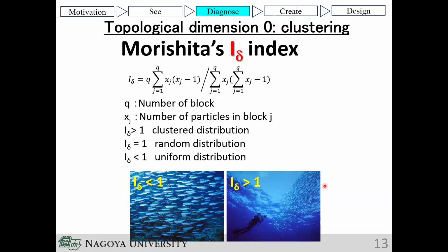Here, we use the Morishita's I-delta index. To evaluate spatial distribution, we employ the Morishita's I-delta index, originally developed in ecology, by dividing an image into Q grids and counting the number of entries x_j in each grid. The index characterizes the distributions. If I delta is larger than 1, the particles are clustered or localized. If I delta is less than 1, the particles are uniformly dispersed.